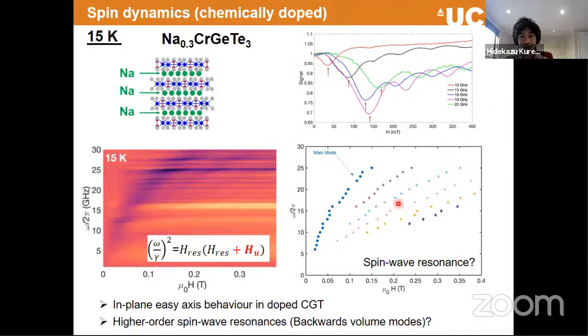On top of it, I just want to mention that not only the main peak, there are significant multiple satellite peaks, and if you look at this in the same film, we can say that this is probably a backward volume mode, but this is almost a bulk regime, so it's very difficult to figure out what these are coming from. But again, these are open questions, but I just thought that it's nice to share.